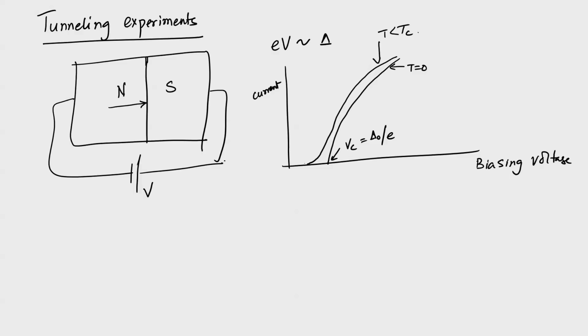Let me just draw it once more. So, that is the property of this junction, that it does not allow flowing of the current, and one gets the tunneling current versus the voltage. So, it is the IV characteristics for this NS junction, and one finds that the current starts taking off only at Vc, the critical voltage, which is equal to delta 0 by e. So, just by noting Vc in an experimental setup, one could find out what delta 0 is.